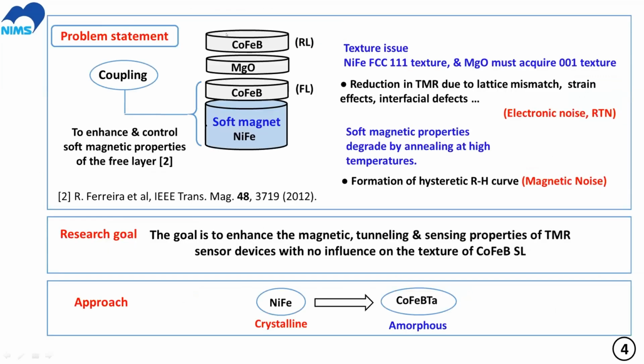So what is the problem statement? The problem statement is very clear and well known since 2012. It was written by Ricardo Ferreira in this article. He said people usually couple cobalt iron boron in the free layer with a thick layer of nickel iron in order to enhance and control the soft magnetic properties of the free layer. The problem happened because of this coupling. It is a material issue, because nickel iron has a face-centered cubic (FCC) 111 texture, and in order to get a high TMR ratio, or a high response from the sensor, MgO must acquire 001 texture out of plane in order to improve the tunneling property across the barrier.